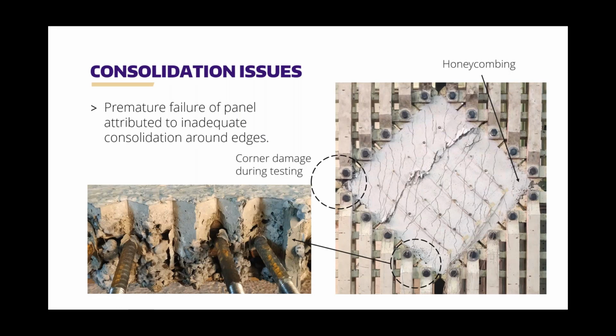So there certainly were some issues with this panel, and we think that's why we're seeing what we're seeing in that plot. So we're seeing if we can retest these panels. It would be great to really see if that's what the cause was, because certainly it's showing a different trend than the other sets of tests.